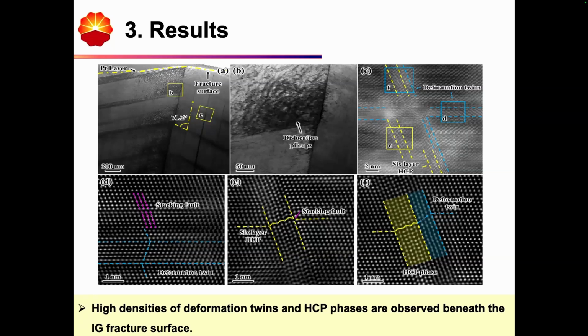This can demonstrate that the HCP phase is actually an unsteady state for the MEA alloys during deformation, but due to hydrogen trapping behaviors, it will complete the continuous transformation from the HCP phase to the deformation twin, resulting in this kind of complicated structure.